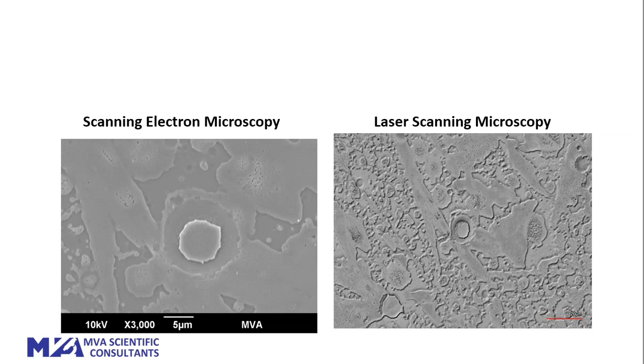We have another set showing an SEM and a laser scanning image of the same feature. Within this region you can see the change in topography — it becomes more striking in the laser scanning image, with quite a bit of modeling and change in surface topography. There are some flat areas, which are probably the original glass surface, and areas in between where glass has been removed — very easy to see.